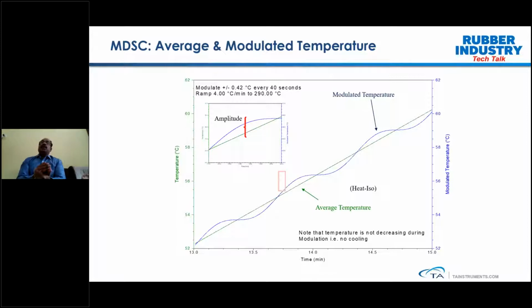In MDSC, what we are doing is, again just like modulated TGA, in modulated DSC, instead of applying a linear ramp, we apply an oscillatory temperature ramp at a fixed amplitude and period. So in this particular case, if you take a small portion of the heating ramp, you can see a sinusoidal temperature ramp with a variation of plus or minus 0.42 degrees centigrade and a period of 40 seconds. And overall we are maintaining a ramp of 4 degrees per minute up to the temperature of 290 degrees centigrade.